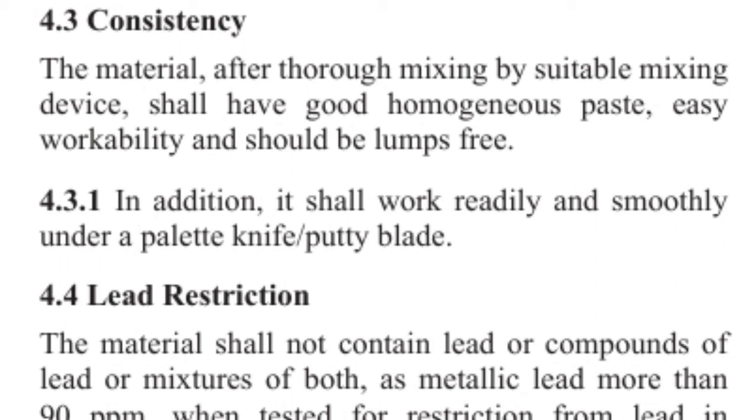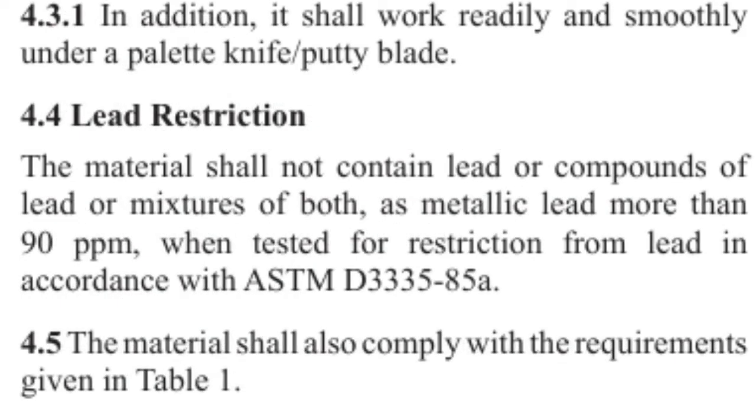Lead is not good for health, and it is not recommended by the IGBC, the Indian Green Building Council. So you need to check whether it is present or not. The standard says the material shall not contain lead or compounds of lead or a mixture of both, with metallic lead no more than 90 ppm when tested for restrictions on lead according to ASTM D3335-85A. So that also gives the lead restriction.